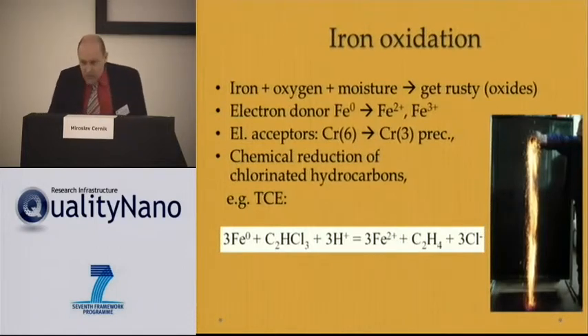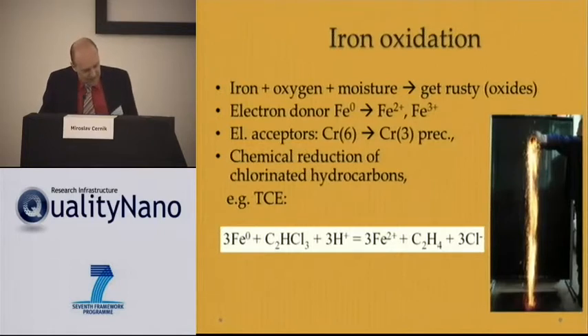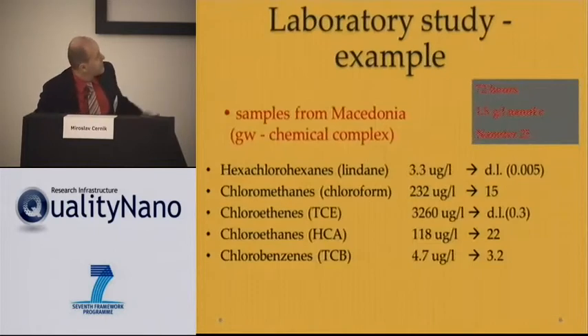The iron nanoparticles are so reactive, like you see in the picture, that of course they react with the oxygen in fire. And our task is to use these particles, to somehow change them to be able to treat contaminants like the chlorinated hydrocarbons here. Trichloroethylene is changed by the reaction with iron to ethene, which is of course not so toxic like the original chlorinated hydrocarbons.